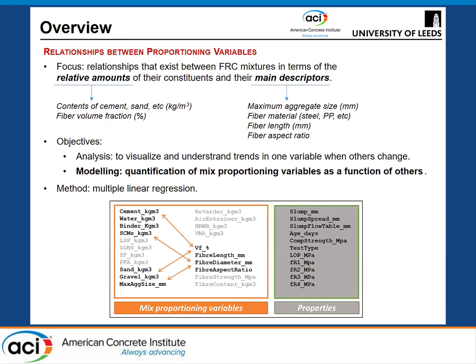And the objective was not only to model in terms of obtaining equations that can give me approximate coarse aggregate amounts or typical coarse aggregate amounts for a mix depending on the aspect ratio and the amount of fibers that I have, but also to develop plots and graphs that can be used to understand, to learn about the material. And the method, it's as simple as multiple linear regression.